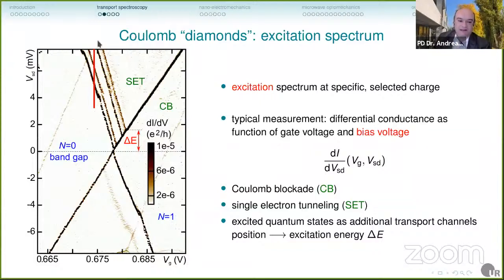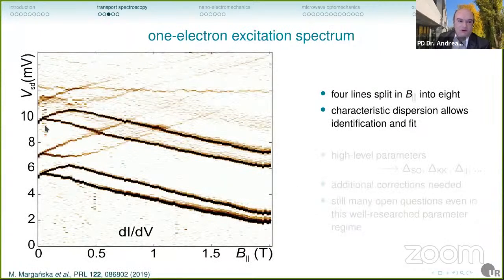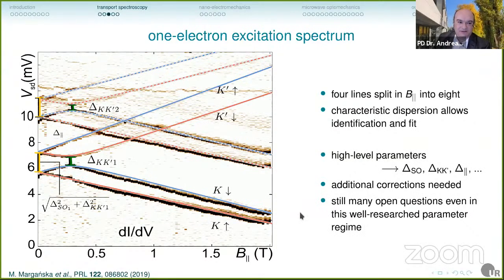Now, this is most interesting if you look at dependence on additional parameters. So for example, we can now take cuts along such a red line here, 1, 2, 3, 4 lines, and apply a magnetic field parallel to the nanotube. You can see the lines split, they show very distinct dispersion, and that allows us to identify them and fit them, actually with a straightforward single particle Hamiltonian in this case. And we can extract the high-level parameters like the spin-orbit coupling, the valley mixing, and so on. You can see that for this field range here around 1.5 Tesla, we end up with essentially pure spin and valley states. So this is a very well-researched system by now.